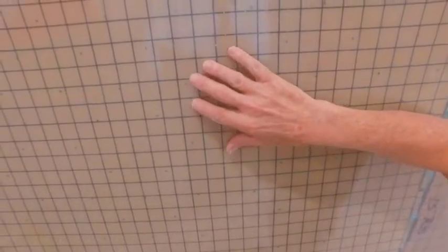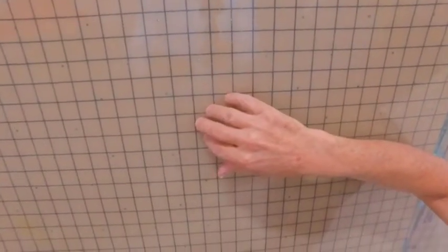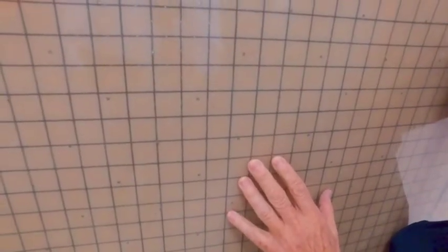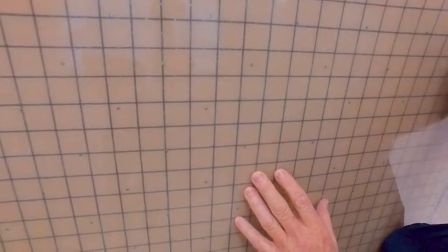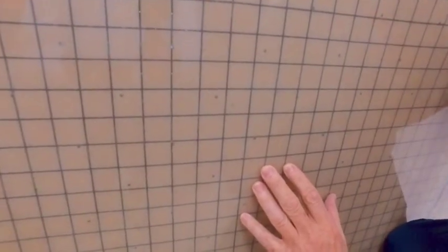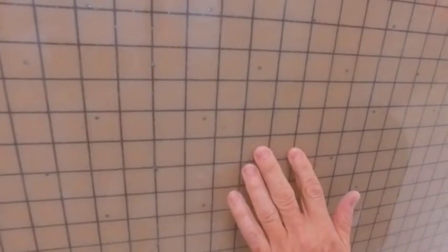So this is an example of infusion working as intended. The fact that there's a 35-ounce quadraxial on here that you can't see is an indication that both the epoxy and the pressure from the vacuum bag is working as intended. 1 atmosphere of pressure from the vacuum is equivalent to 2,116 pounds per square foot pushing on the inside of the mold. But the clarity that you see here is a good indication that everything's working according to plan.